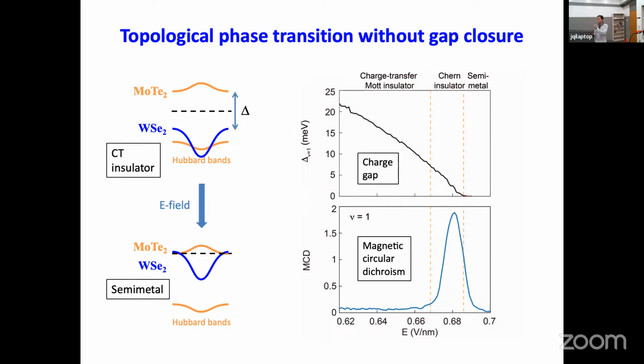So we can also do simultaneous magneto-optical measurement on the same sample to look for spontaneous time reversal symmetry breaking, in particular, the magnetic circular dichroism signal from the sample. And you can actually see that this is the turn on of the magnetic dichroism signal. So that's the time reversal symmetry breaking. And above the first orange dashed line here, we actually get a Chern insulating state with spontaneous time reversal symmetry breaking. And then the Chern insulating state is gone with further increase in electric field because the system turns into